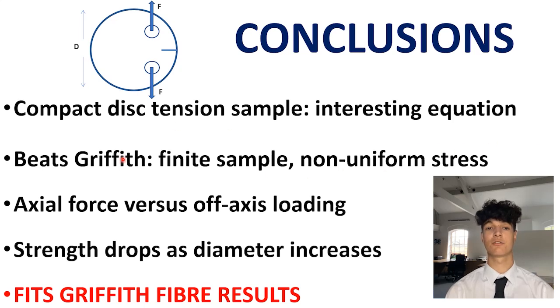It beats Griffith's because it uses a finite sample and uniform stress isn't needed. The actual loading gives a result like Griffith's, but better, because the force must go to 0 when the crack reaches the end of the disc diameter. Off-axis loads introduce bending, which gives a size effect. The disc gets weaker when it is bigger. Remarkably, the equation even fits Griffith's original 1920 results on glass fibres. Fine fibres are stronger. Now, I want to go to the lab and get experimental results. Thank you for your attention.